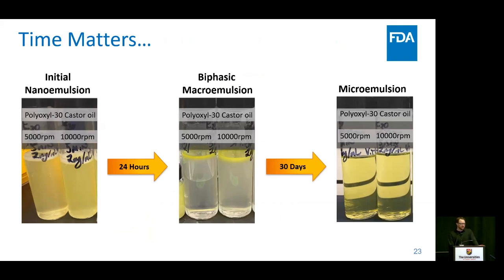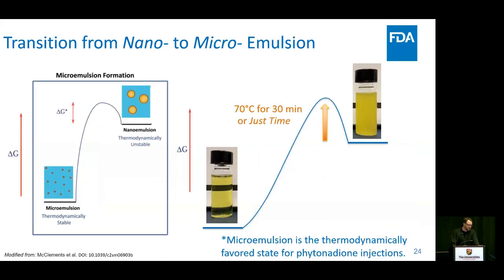So what this is telling us is that at this specific composition that this product is formulated at, the favored state is the microemulsion. So it is a true microemulsion system. And so basically what we were able to show is that the nanoemulsion will go to a microemulsion given enough time or temperature. And so these are manufacturing considerations.